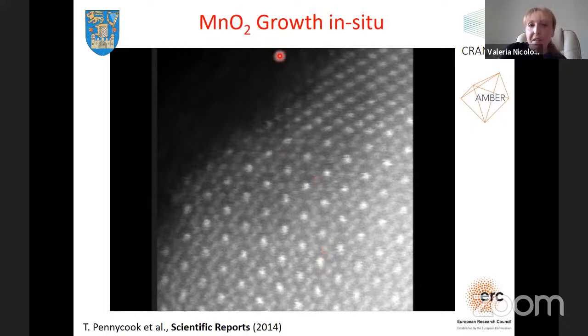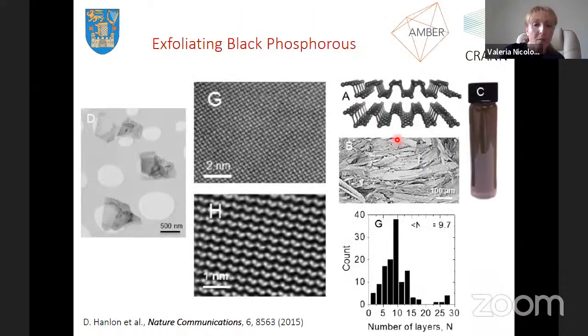And this was a very, very important result, because we use manganese dioxide a lot in our supercapacitor applications. And understanding the equilibria that happens when you synthesize this material and the stoichiometry balance that you get with MnO, it's extremely important. So we could start tuning the temperatures at which we could synthesize MnO2.